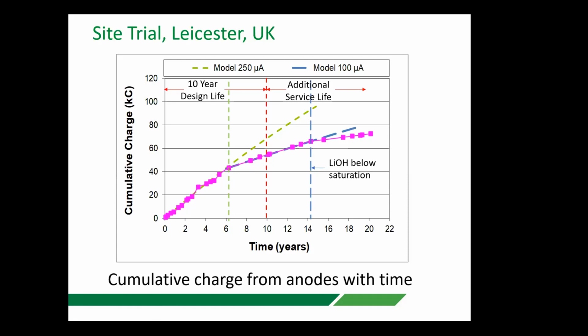But both of these things could be dealt with. Here you can deal with this one by increasing the amount of lithium hydroxide. And we've done that with subsequent designs where we increased the lithium hydroxide content by up to 10 times. This could be dealt with to an extent by increasing the porosity of your encasing mortar.